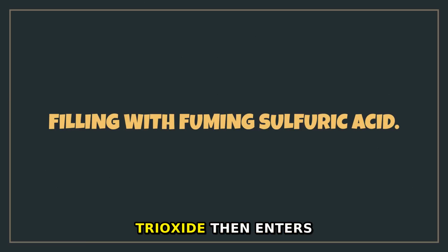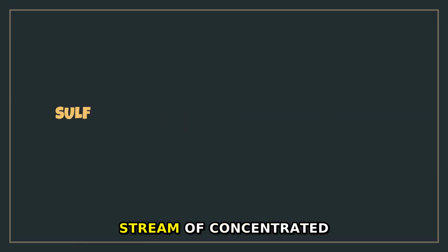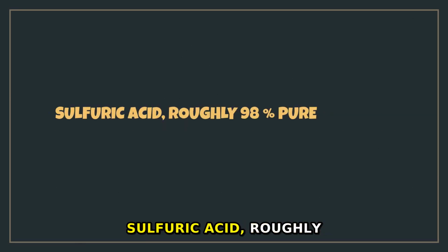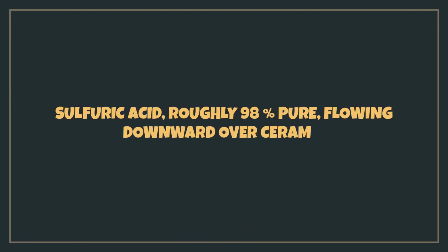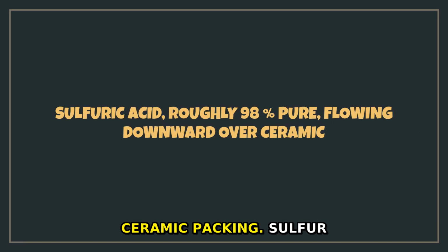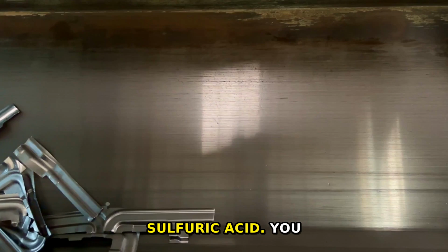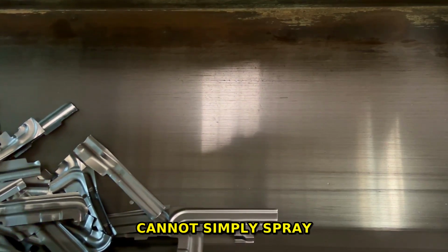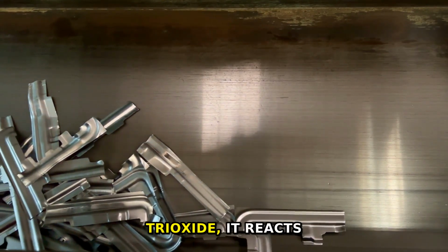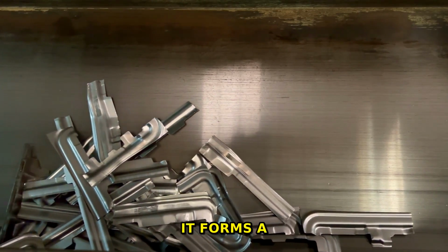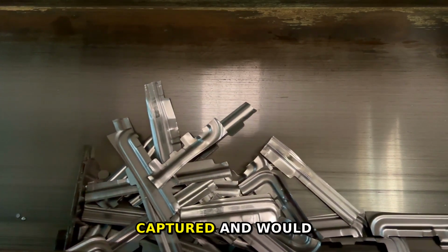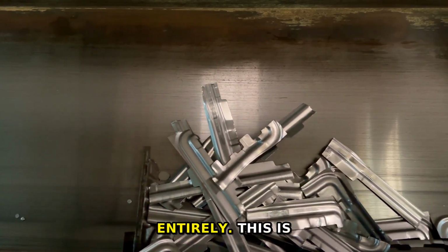The sulfur trioxide then enters absorption towers, tall columns where it meets a controlled stream of concentrated sulfuric acid, roughly 98% pure, flowing downward over ceramic packing. Sulfur trioxide reacts with the water component of this acid to form more sulfuric acid. You cannot simply spray water at sulfur trioxide, it reacts so vigorously that it forms a fine acid mist that cannot be captured and would escape the absorber entirely.